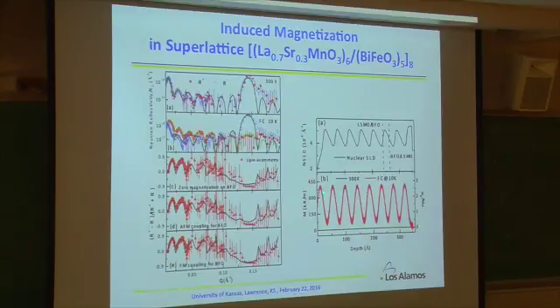As you can see over here, here is the LSMO. It's ferromagnetic. You see that kind of magnetization, it's much, much higher. However, when you go to bismuth ferrite, keep this in mind, bismuth ferrite is an anti-ferromagnetic material. But over here, actually, it goes ferromagnetic. That's more like a coupling effect. Because you put them together, you change the anti-ferromagnetic material into a ferromagnetic material.